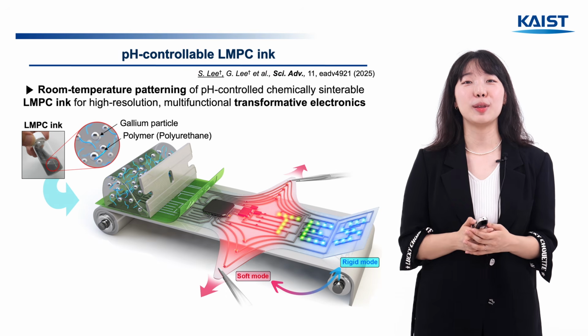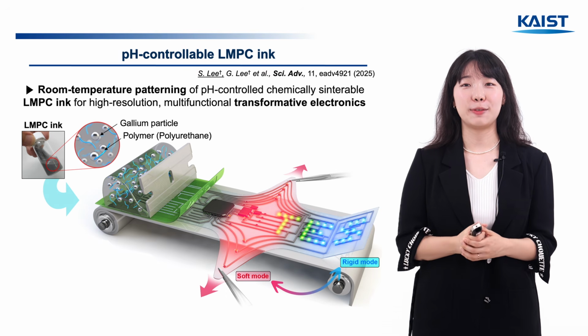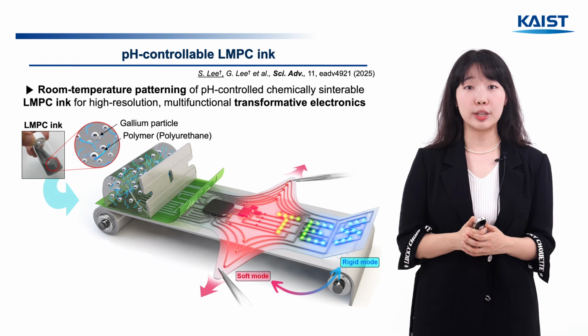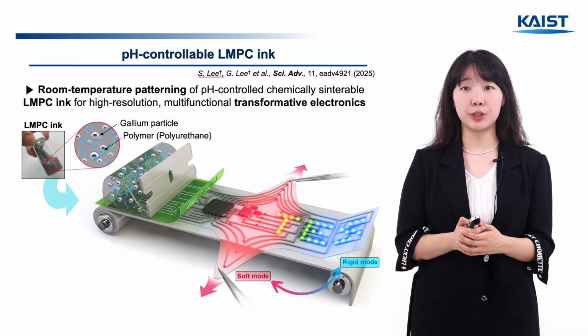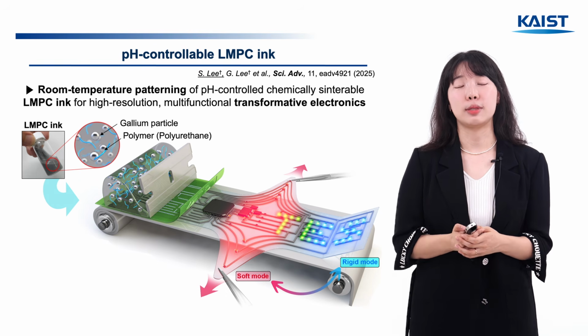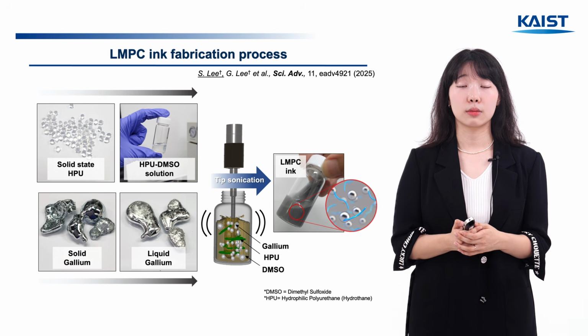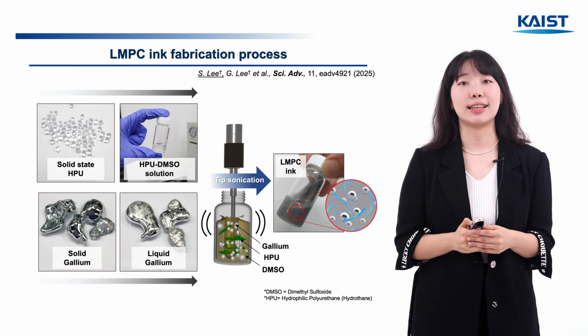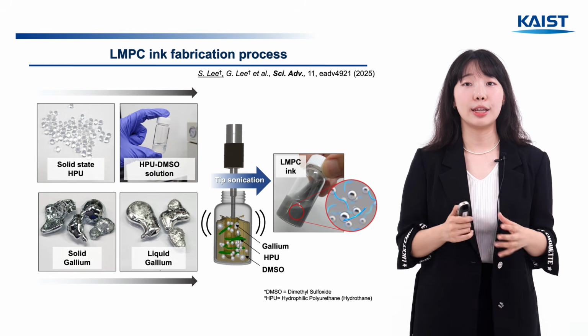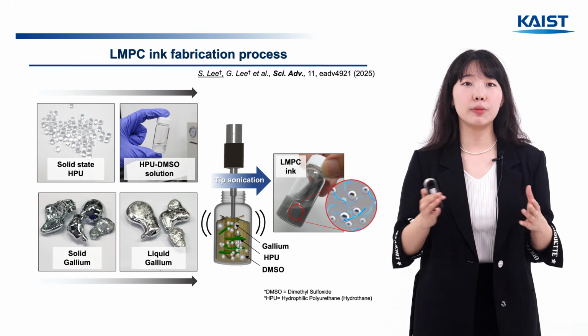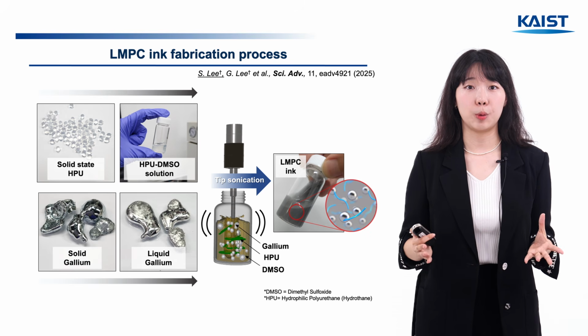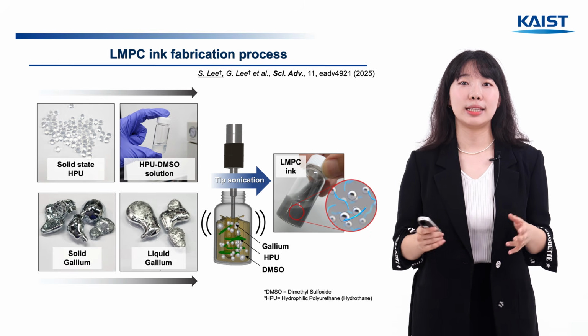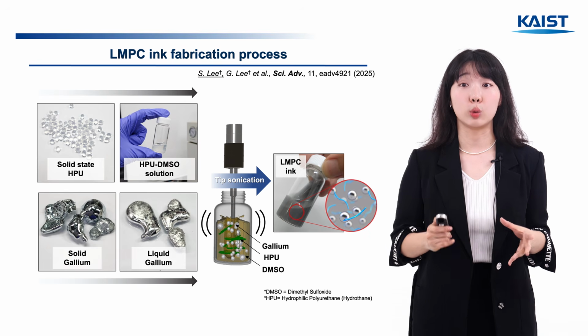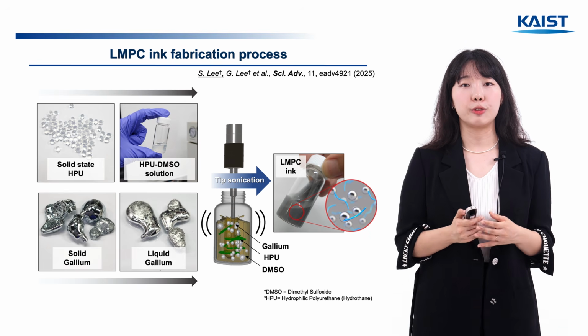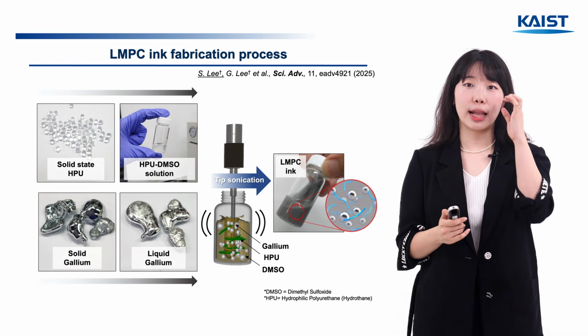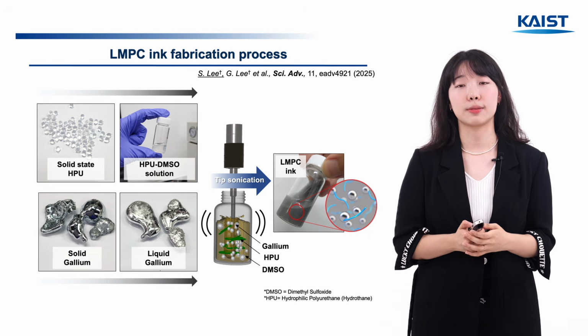So to solve this problem, in this study, I developed a stiffness-tunable electronic ink that can be printed at high resolution at room temperature while remaining free from the IMC formation. The fabrication process is as follows. First, solid hydrophilic polyurethane is dissolved in dimethyl sulfoxide, DMSO. Liquid gallium is then added and dispersed into a polymer solution through tip sonication. The result is an LMPC ink with gallium microparticles dispersed throughout.